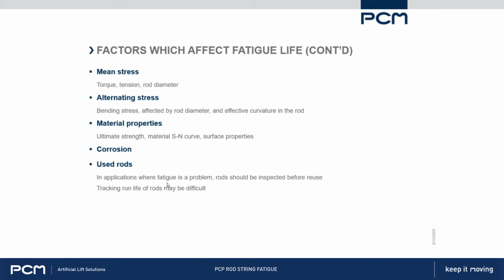Ideally, you're doing a non-destructive testing method that's looking for fatigue cracks. You cannot see fatigue cracks with the naked eye. So when you're doing a visual inspection of rods, obviously, if you see anything that's got corrosion pits or visible wear or any kind of visible damage, you're not going to reuse those rods. But you can't see the fatigue cracks with your eye, so you need to use a different testing method to find those if you have that capability.